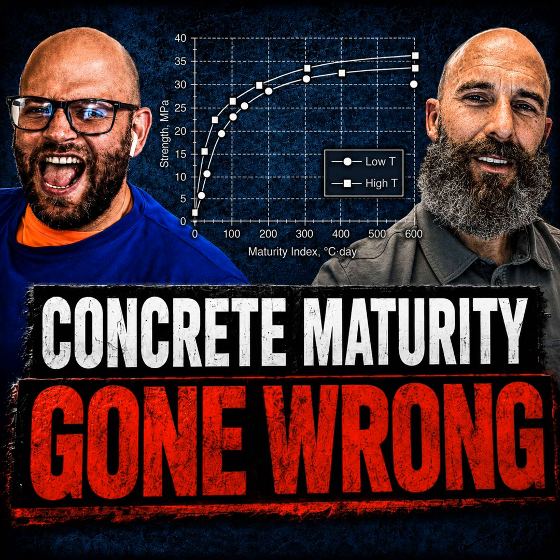Mm-hmm. And what happens if I strip forms too early? People get hurt. Right. Now, if I choose the opposite, and now instead of telling me to strip forms way too early, it tells me to strip forms instead of at 8 hours, at 24 hours. What's happening now? Could impact your schedule. Your critical path. Right. And 24 hours, folks, when I'm supposed to rip and strip at 8, my boss, Seth, is going to roast me. What do you mean we're waiting 24 hours?